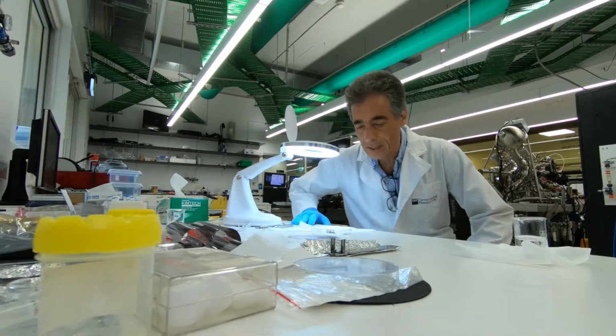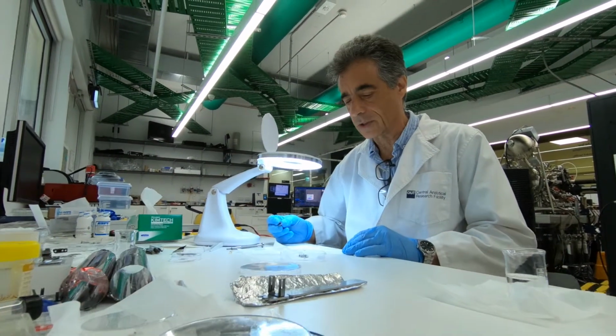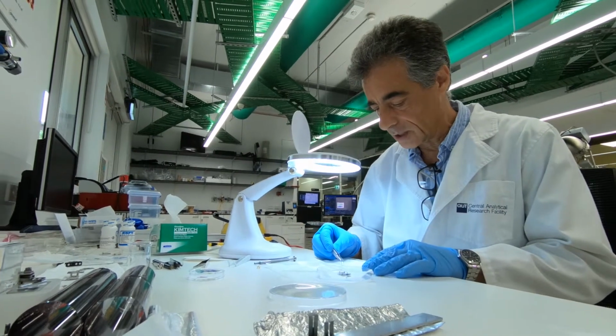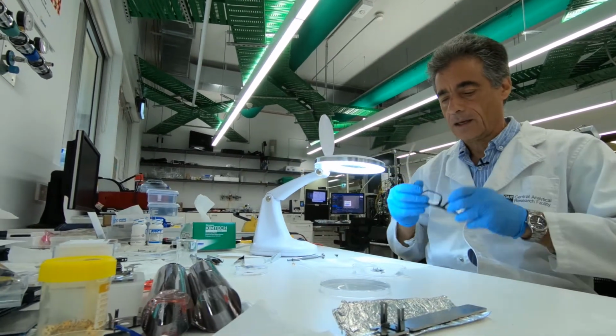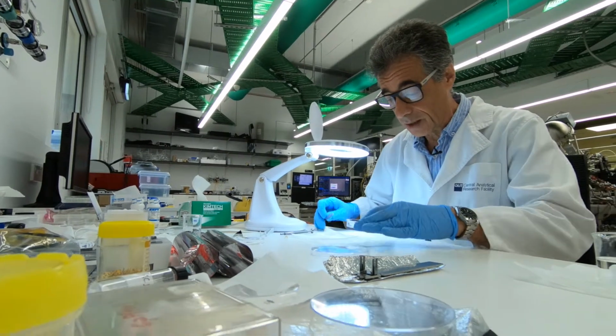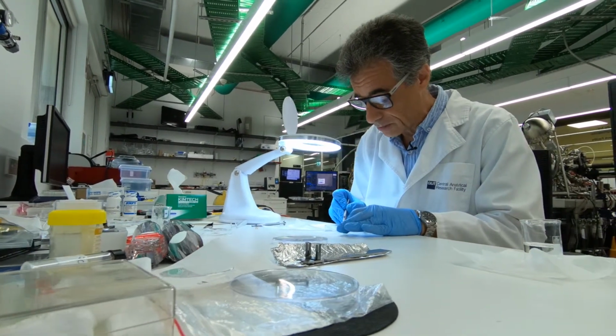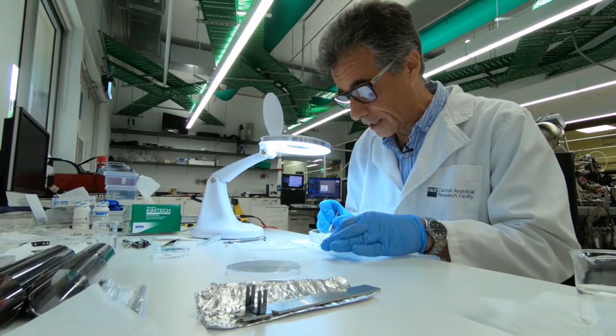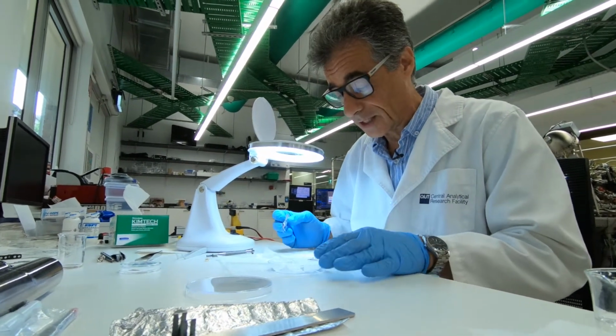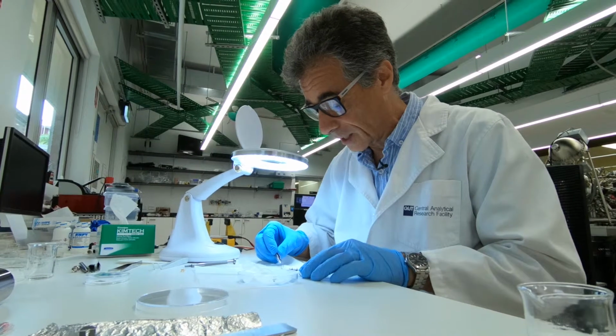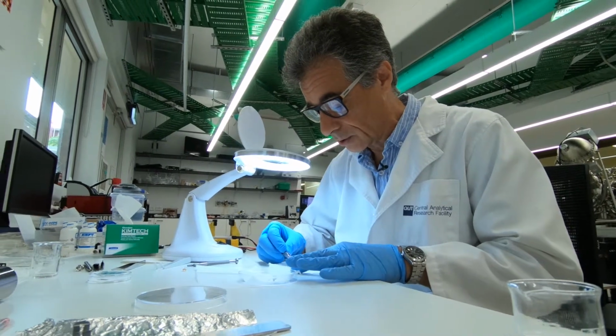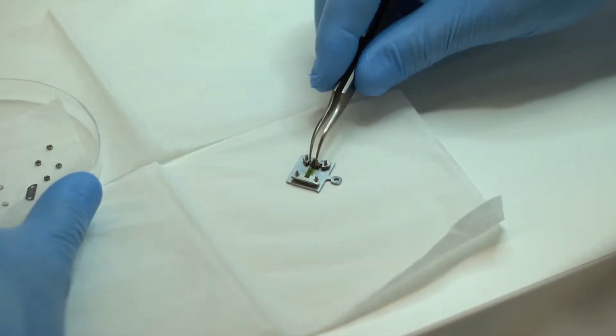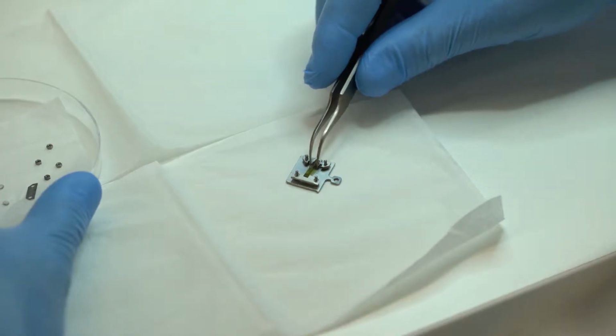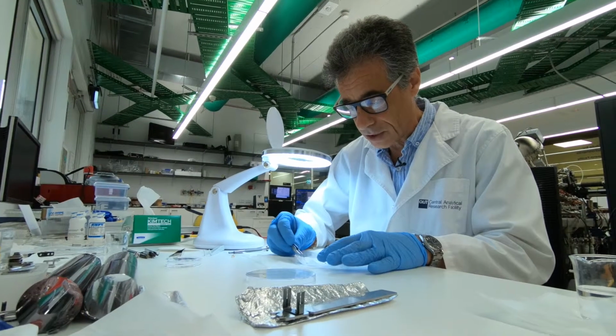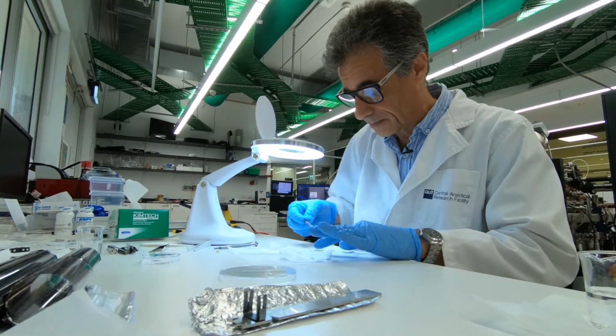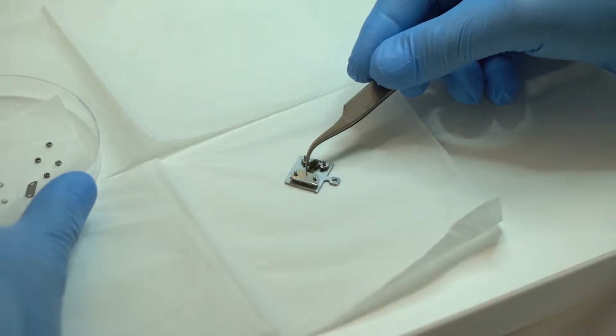Okay, now that we have prepared our sample, we are going to mount it onto the sample holder. So this is our sample, and this is the sample holder that is usually made of molybdenum. This one is made of tantalum, a very high resistant material, a refractory material that can resist very high temperature. So what we are going to do, we are going to put the sample across here. We are going to put some special attachments here to make a good contact.